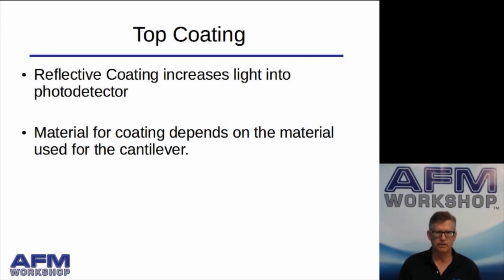So the materials for coating probes depend on the type of probe, the type of cantilever the material is made out of. If it's made out of silicon, quite often you use aluminum. If it's made out of silicon nitride, you would use gold. So again, this typically depends on the manufacturer of your microscope.